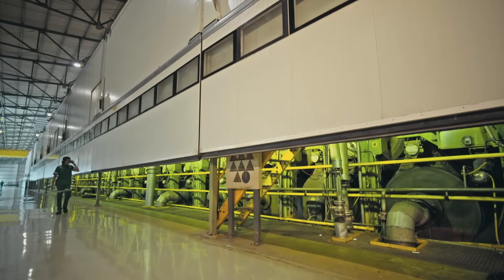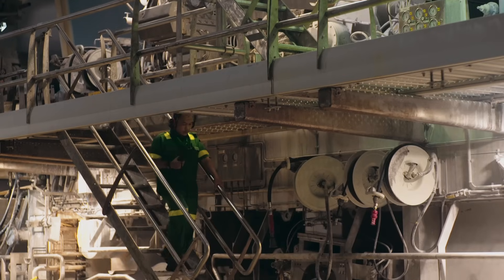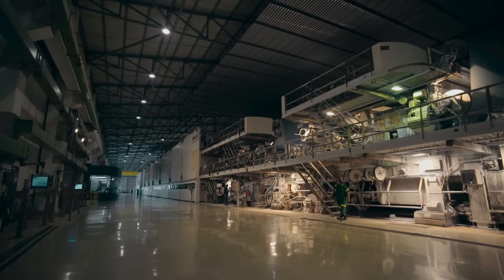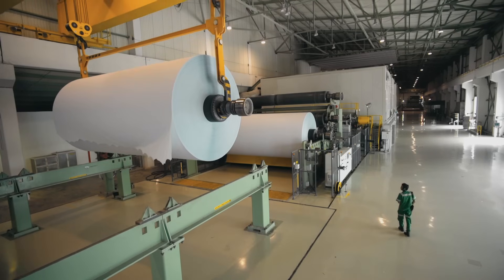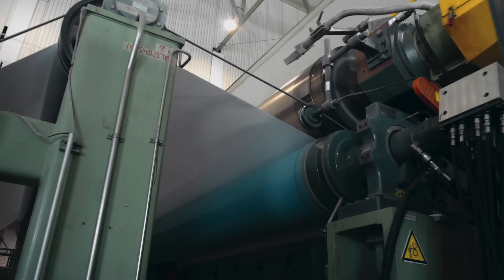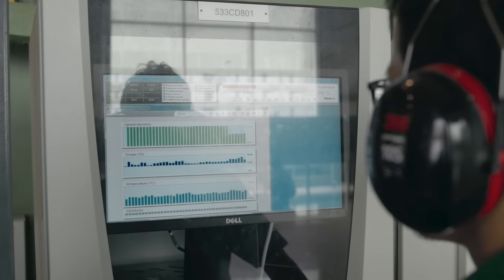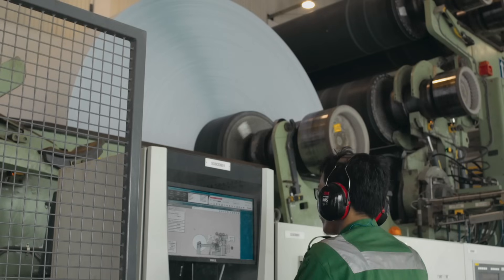Here, the fibers spread and form thin sheets in a process called sheet formation. These sheets are put into a processing machine where 50 percent of their water content is squeezed out. The paper is then dried using several metal cylinders at a temperature of around 100 degrees Celsius.